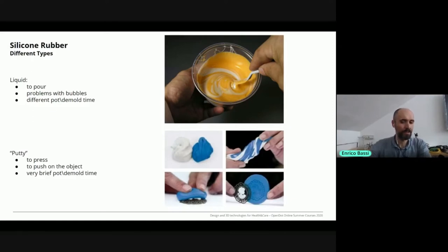Okay, so my suggestion after this lesson is really to invest 30 euros in a bit of silicone and some material that you can cast. The cheapest, easiest material to cast is plaster, because it's enough to mix powder with water, it's non-toxic, very easy to wash away, and super cheap. In plaster, keep in mind that there is what's called acrylic plaster in some cases, that is meant for casting, and that gives you a much better result, a very smooth finishing. It has a feeling of ceramic a bit. It's a bit more expensive than normal plaster, but it's not expensive, it's not going to be 5 or 8 euros per kilo. And it's really fast, so you can do a lot of experiments with very little. So try it out. It's really fun.